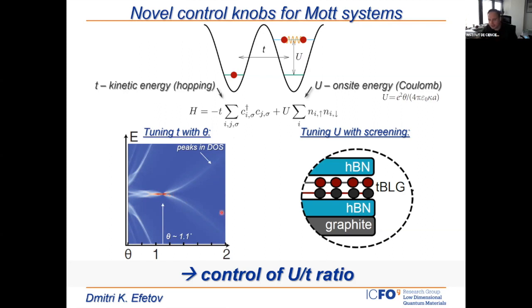U in the problem. Because, as I mentioned, our devices are embedded into a very non-trivial dielectric environment. So usually the twisted bilayer is encapsulated by hBN, which has a certain dielectric constant, but in principle, we can change that dielectric constant. And second of all, we usually have metallic gates close by to the plane of the magic angle graphene. As I will show in a second, we have typically graphite gates or gold gates, which are sitting very close, which we typically use to control the carrier density. But also, these graphite gates are really just a few nanometers away. So we can, in principle, use these graphite gates to screen out interactions out of plane.